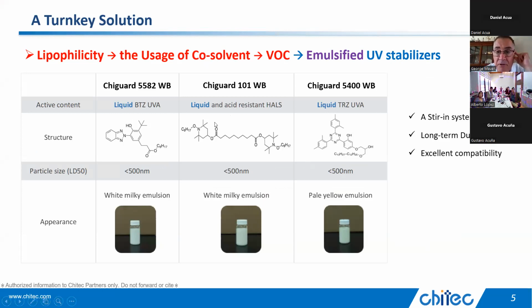The one that goes the best in a waterborne actually depends on what you're looking for. There are some details in there that are hard. For instance, depending on if there are certain colors that you need to protect, or a certain susceptibility to cracking or delamination, depending on what the substrate is, that could change what the optimum approach is. A great starting point is using a 50-50 mixture of the 5582 and the 5400 WB. It's a really good UV absorbing mixture.